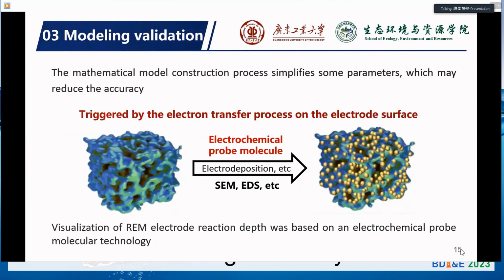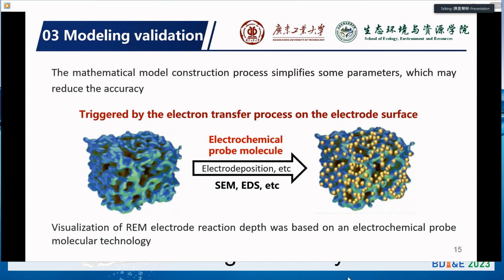So the above information is based on the mathematical process. We can't directly see whether it is right or wrong, so we use another method to validate our model and assumptions. Now we use electrochemical imprinting methods. We need to add a probe into the system, and at a certain potential applied onto the surface, there would be either electrodeposition or electropolarization process to capture the reaction sites. And we can visualize the results by SEM and EDX analysis.